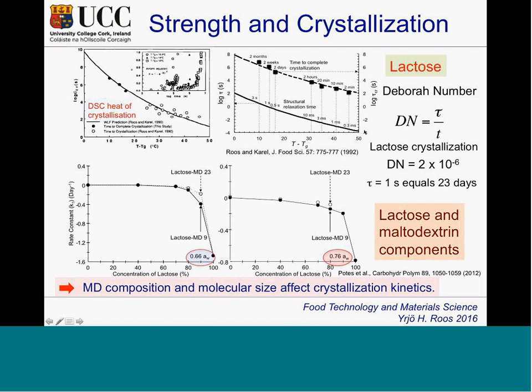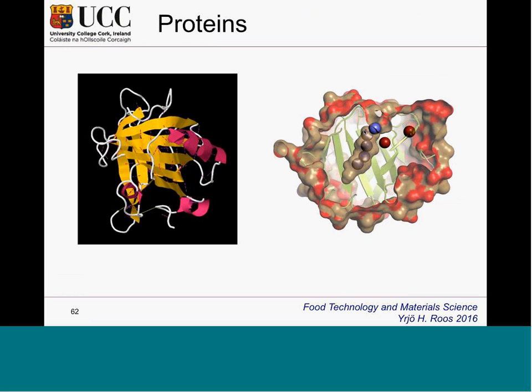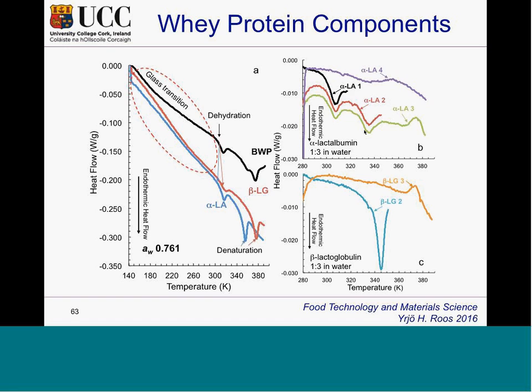Proteins are very different. We have some initial work on their transitions, and this is showing a rapid picture of protein components. A transition may be found at low temperatures, but I will comment on that. Then we have an endotherm that is not well described in the literature, but there is some data on that, and then denaturation. If we look at albumin, there is this dehydration transition, and then also a reversible change of the protein, and then aggregation at high temperatures. Beta-lactoglobulin is somewhat different because its dehydration happens, but it's slower, so it's not visible in the scan.